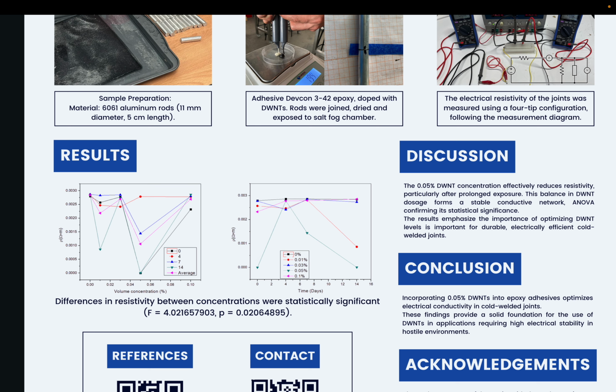After 14 days of exposure, the samples with 0.05% DWNTs demonstrated a significant decrease in resistivity compared to both the control samples and those with other concentrations. Also, after that, we performed an ANOVA on the resistivity data, which confirmed that the differences between DWNT concentrations are statistically significant. This supports the hypothesis that the optimal concentration plays a critical role in enhancing the electrical properties of